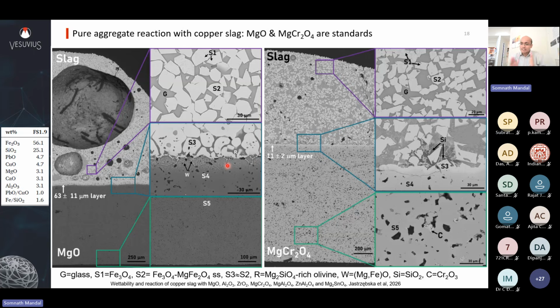So again, you have a basic slag, use a basic brick. You have acidic slag, use acidic brick. These are very early surface level guidances. But when you are going into a specific slag, specific temperature, specific refractory compositions, you have to observe what reaction phases are forming, and you have to actually run tests like induction furnace tests with fingers of your refractory rotating in the slag to get a better idea. And then you have to cross section it and figure out how much of these phases are forming.